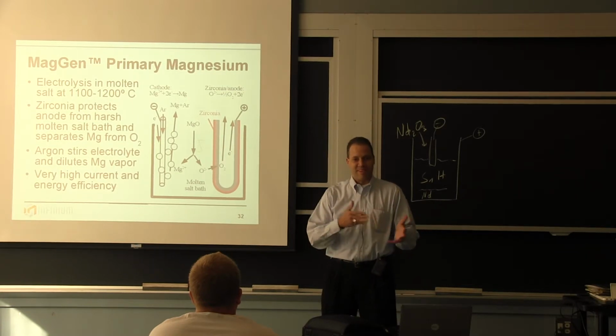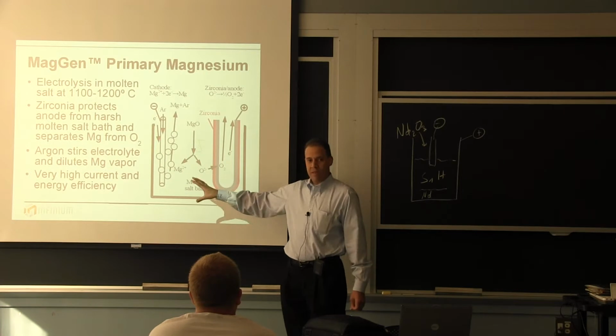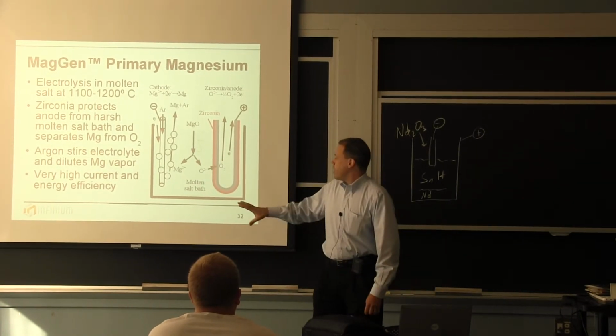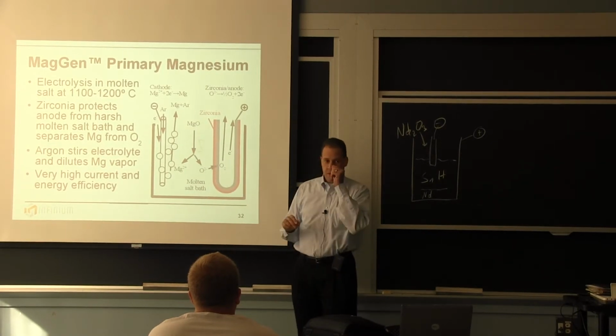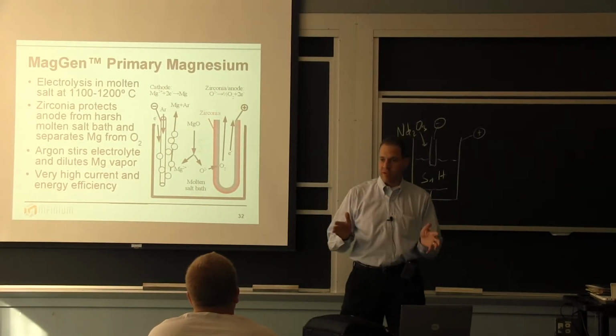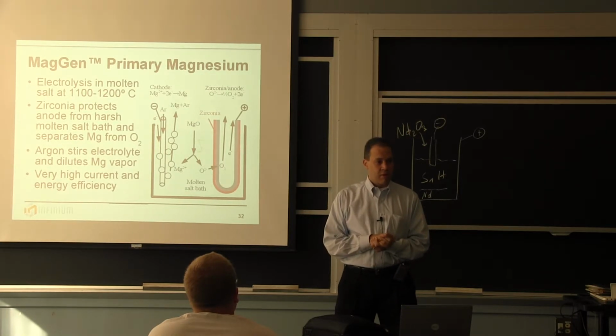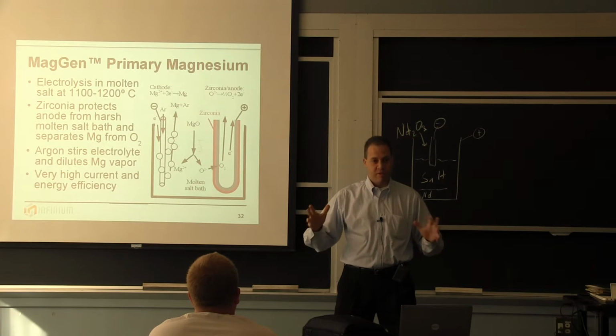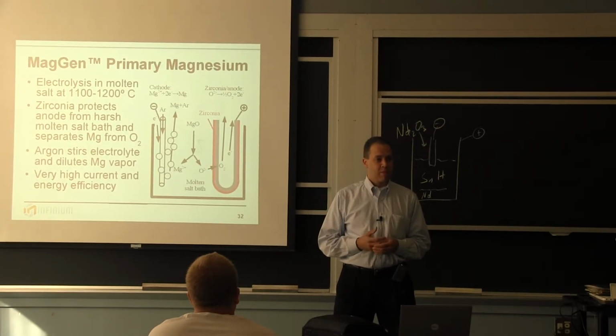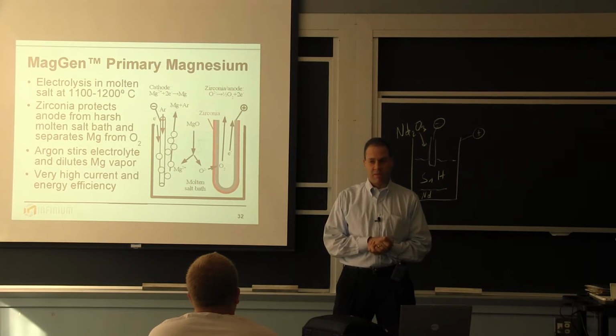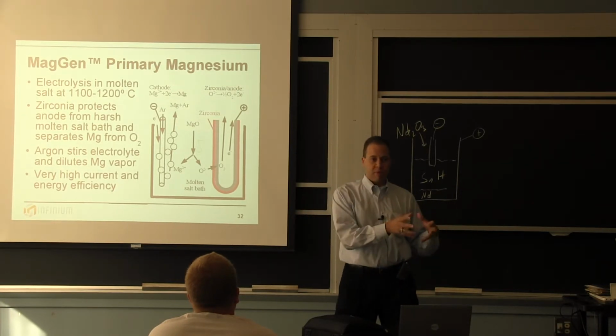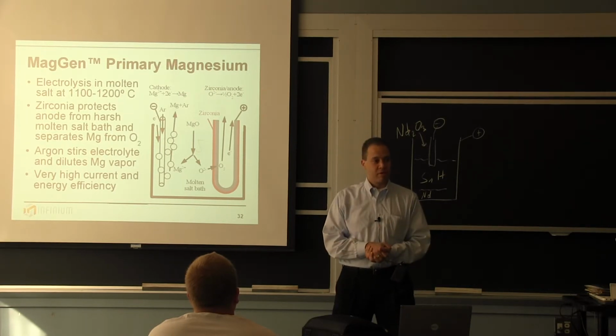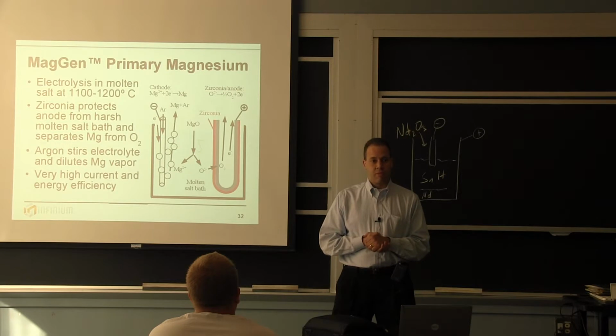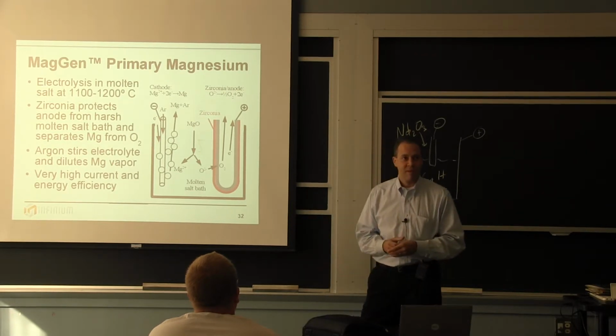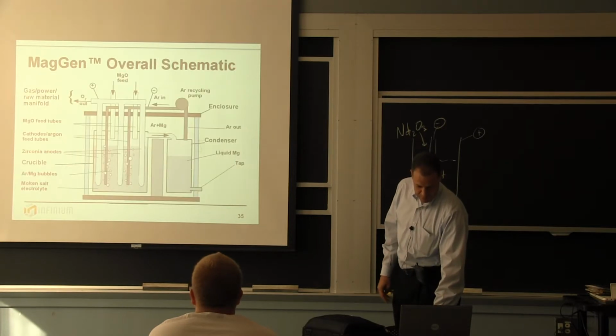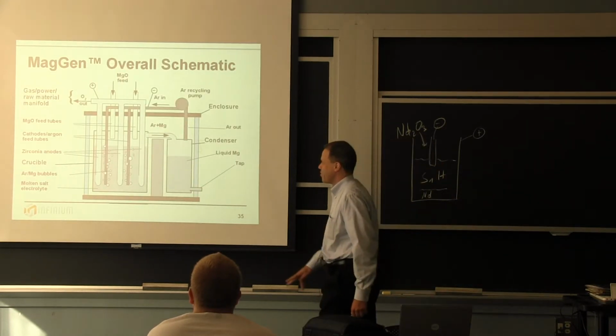And I can talk about it because he's at BU, he's published this. Turns out magnesium fluoride, calcium fluoride eutectic, unlike cryolite, does not attack the zirconia, such that we've seen in 500-hour tests, you get about 100 microns of zirconia corrosion. So if we run for 5,000 hours as our target lifetime, that's a little more than 6 months, 1 millimeter of corrosion. And if they last for that long, then the cost of zirconia tubes per pound or per kilogram of magnesium ends up being very low, a small fraction of our total cost. So that's the enabling breakthrough here. And if you're interested, I can talk about why that is. But okay, this is something like how it would look in industry.